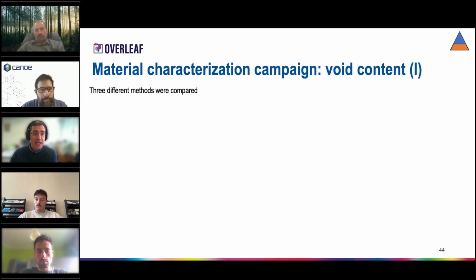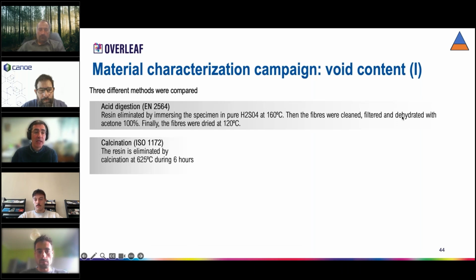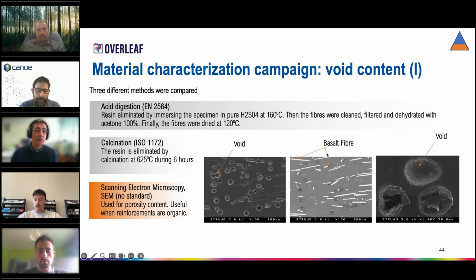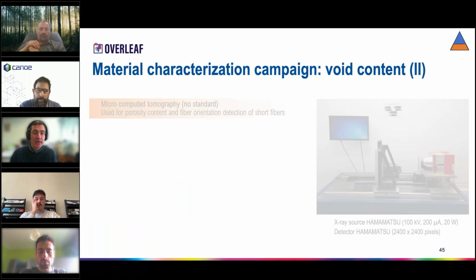Also, at the base of our pyramid, we have performed a characterization of the void content. We have used three different methods. Two typical methods, acid digestion and calcination, according to the standard. But since we first tested materials without reinforcements, and since Canoe has shown in this presentation that we have used some materials with organic fibers, if we use acid digestion or calcination, we can damage these fibers. So we have used a third alternative method, that is scanning electron microscopy. So taking pictures of the side or in the middle of the specimen to detect voids or to detect the quantity of fibers.